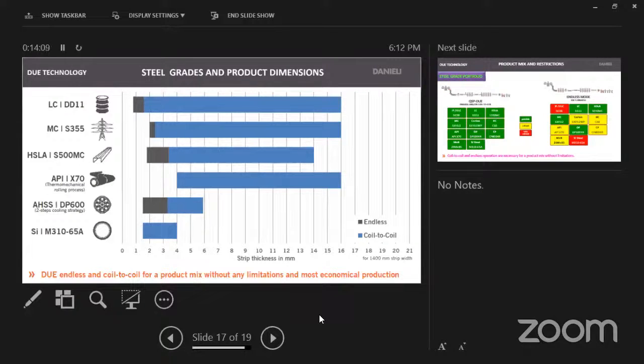Similarly, advanced high strength steel you can produce in coil to coil mode, from 3-4 millimeter we are showing here, but nowadays you can produce up to 6 millimeter also in endless mode. This is because the high speed shear capacity is more nowadays, so you can cut up to 6 millimeter. So advanced high strength steel you can produce, but API grade you cannot produce in endless mode, and not in conventional CSP mode. For that we require a certain temperature and certain space to make the proper crystallization.